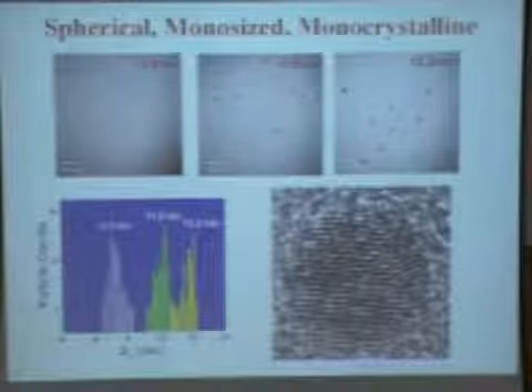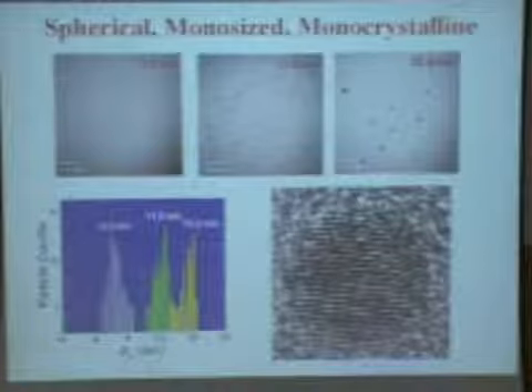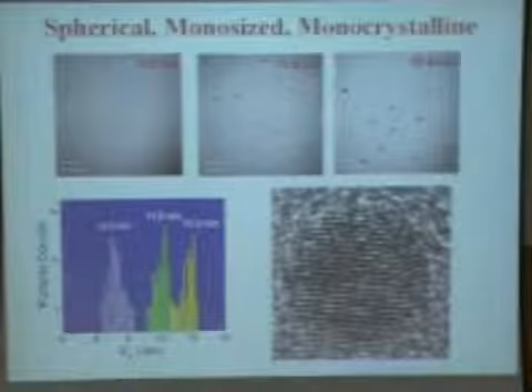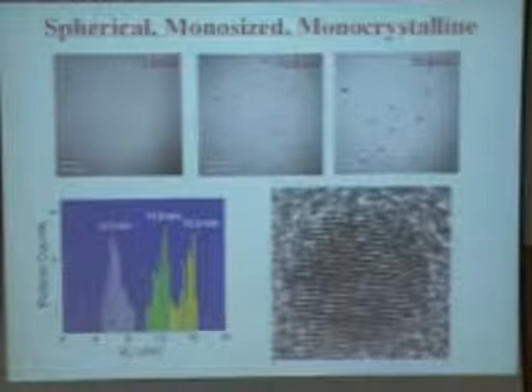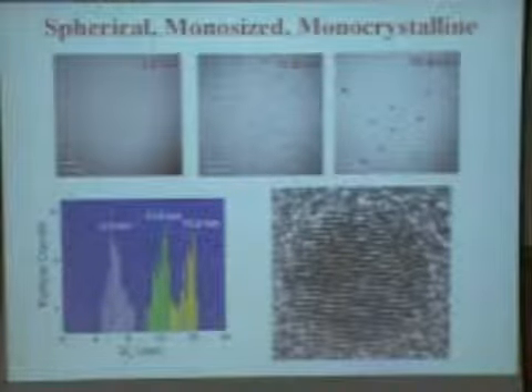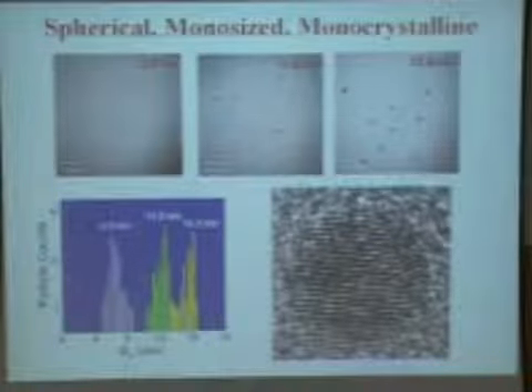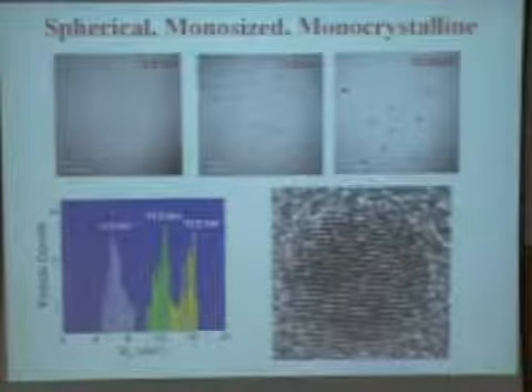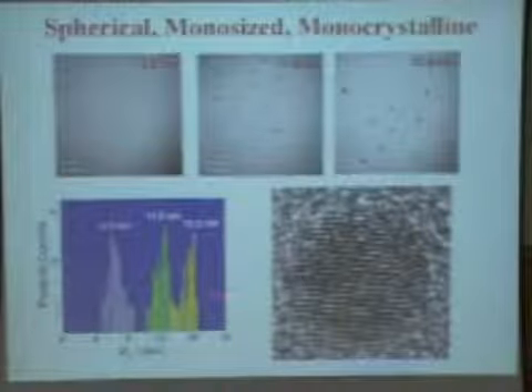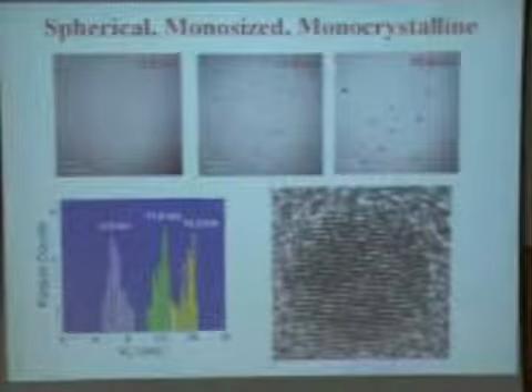If you look into the transmission electron microscope, you can see that by giving a different voltage to the differential mobility analyzer, you can select particles of different sizes: 6 nanometer, 11.2 nanometer, 15.3 nanometer. You can measure their size distribution, and in this case the geometric standard deviation is less than 1.04. For a monosize distribution, the geometric standard deviation is 1. So this is very close to a monosize distribution. If you go to the high resolution transmission electron microscope picture, you can see the lattice imaging. They are monocrystalline and spherical.